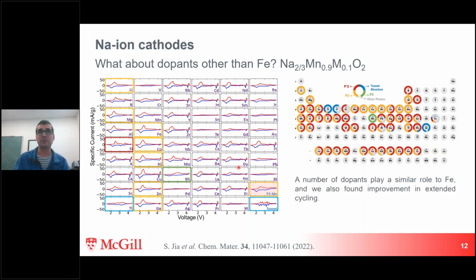The other thing we found that was really interesting, so this is a little bit of an aside, is a high voltage peak appeared in a lot of dopants. If we think about what's in this material, there's manganese, which gets oxidized down at 2 to 3 volts. It doesn't get oxidized up at high voltage. Sodium doesn't change its oxidation state. These dopants like cesium or calcium, they don't change their oxidation state. So this peak has to be oxygen. So we found a number of dopants that induce this anionic redox.